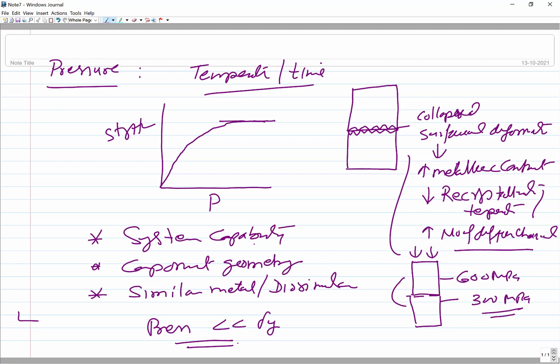Too high a pressure also cannot often be applied due to system capability. For developing the diffusion bond of very large size components, we need to apply the desired minimum pressure, and that cannot be applied because of the system capabilities. You may not have those very high capacity presses to induce the desired pressure. And when we go for very high pressures, the system cost becomes high, it needs much better control, and it involves more complex procedures. So that makes the process a little unpopular.